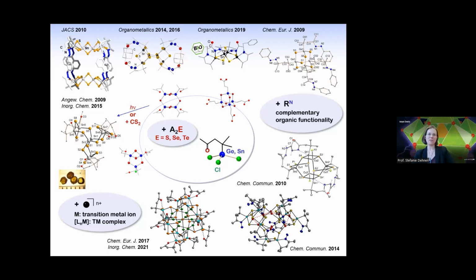Okay, so in terms of aromaticity, the answer is that we cannot tell yet, because the aromaticity has only been proven by quantum chemistry. The aromatic properties have been studied on metal clusters, and they have been the most effective for bismuth clusters. And you can imagine that for bismuth, it's really difficult to have an experimental proof, as we have no NMR handle, it is no Mössbauer core or whatever. So it's really difficult to prove in an experimental manner, although we are doing that in an indirect way now. But so far, we just calculated that.